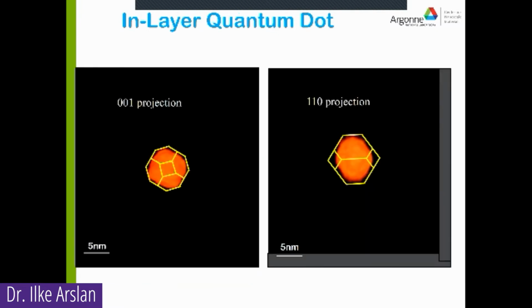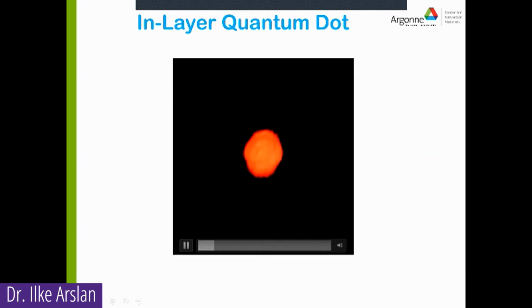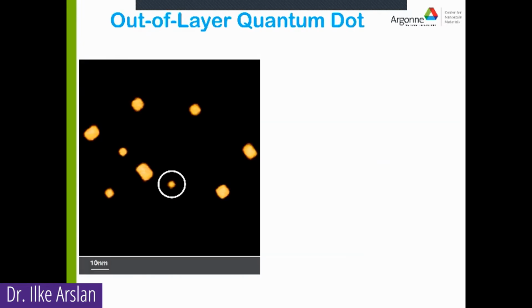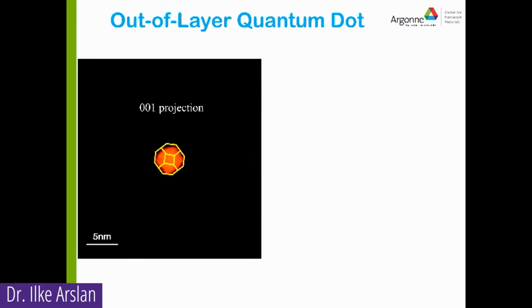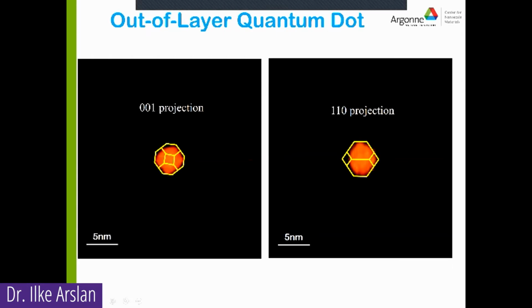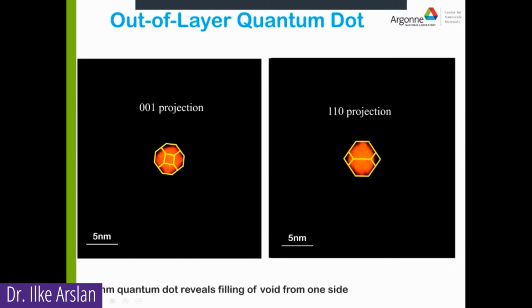So we did some analysis on the particles. So this is a particle, a quantum dot that's inside the layer. And you can see that it fits the shape that it should be in the 001 and 110 projection. And here's a movie of the quantum dot itself. This one is about 7 nanometers in diameter, and it looks symmetric. Now, if we look at that out of layer quantum dot and do the same thing, it's subtle, but you can see that there is some of the quantum dot that's not quite symmetrical here, missing. And if we look at it in the 110 projection, it's missing there. And this is the flip side of it, 180 degrees. This is only 3.5 nanometers in diameter. And what we're seeing is that it's filling a void from one side to the other.